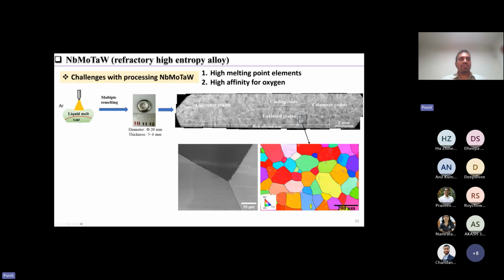So recrystallizing these materials is very tough. You might have to do material processing at about 1800 or 1850 degrees C, so that these materials don't crack, and then you can recrystallize those. And these things you have to achieve under extremely high vacuum to avoid oxygen pickup. So by doing this process, he was able to form this region of equiaxed grain in the buttons, where you can see recrystallization as these small grains form on the grain boundary triple points.